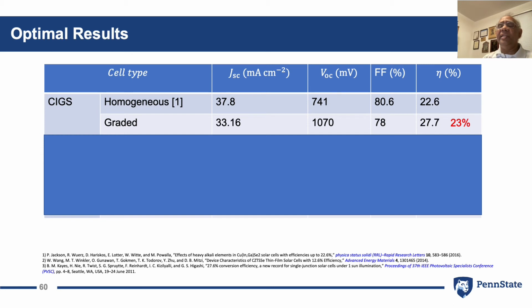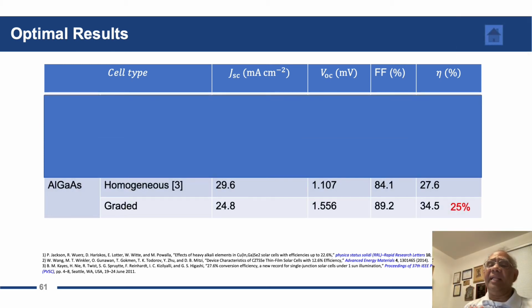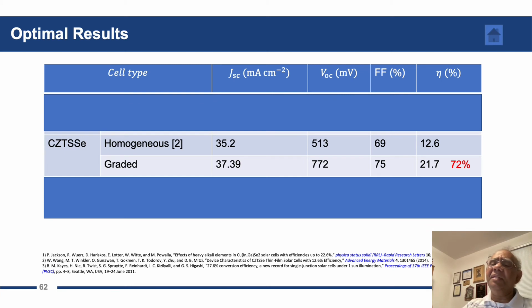CIGS solar cells with a homogeneous bandgap have 22.6% maximum efficiency. Grading, we found out, can increase the efficiency to 27.7%. That is an increase by almost 1/4. For AlGaAs solar cells, the efficiency increased from 27.6% to 34.5%, again by 1/4. For CZT SSE solar cells, bandgap grading increased the efficiency from 12.6% to 21.7%. That is an increase, an astonishing increase by 3/4.